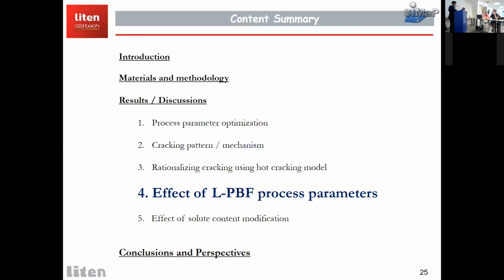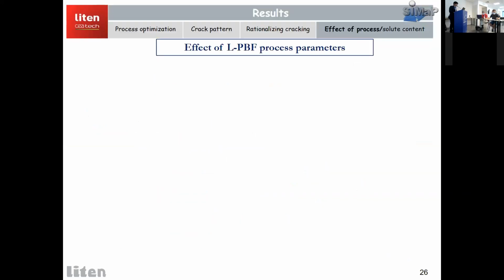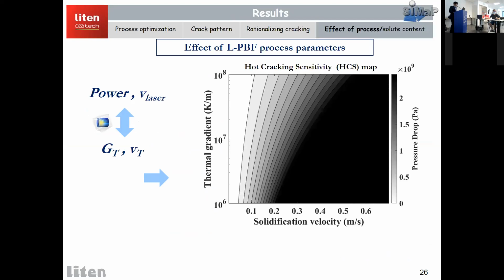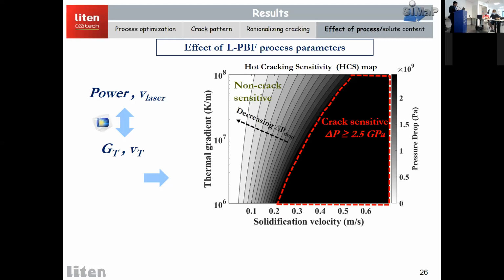Now let's try and understand whether we can find some parameters which are less sensitive to cracking or not. So to do that, we took a range of laser powers and laser speeds, and we linked them to the thermal gradients and solidification velocities with our thermal simulation. And we generated this hot cracking sensitivity map. So in this map, on the y-axis you have thermal gradient, on the x-axis you have solidification velocities, and on the z, you have the pressure drop. The black region here indicates the crack sensitive region based on our critical pressure drop of 2.5 gigapascals.